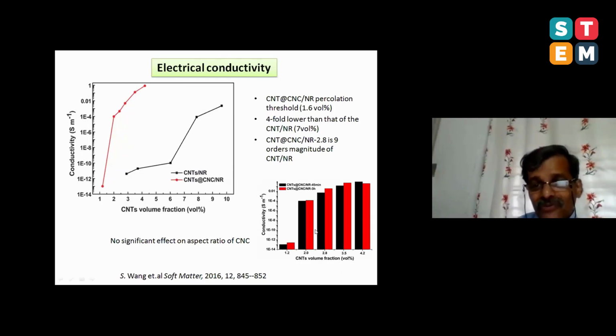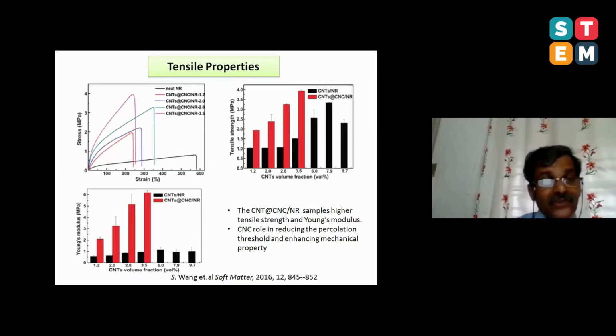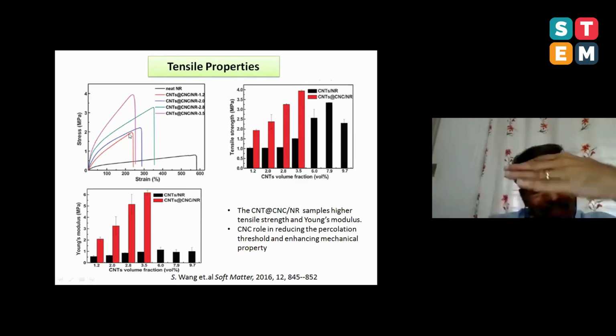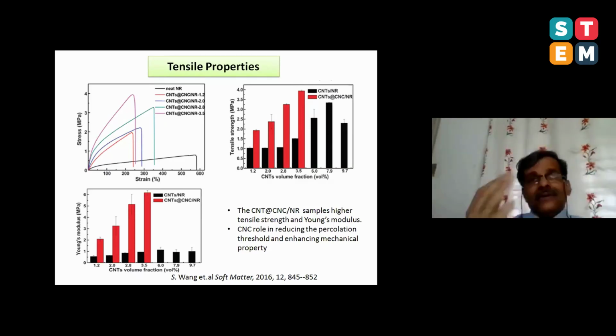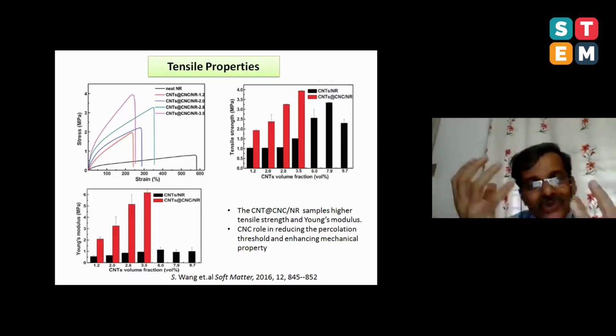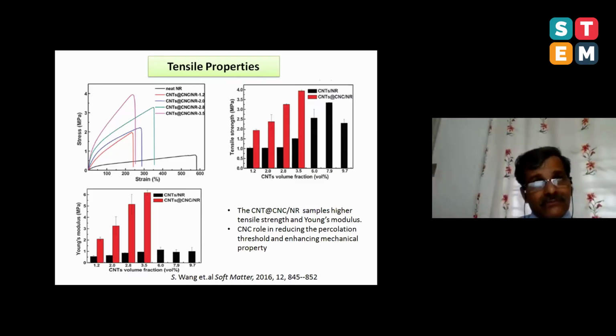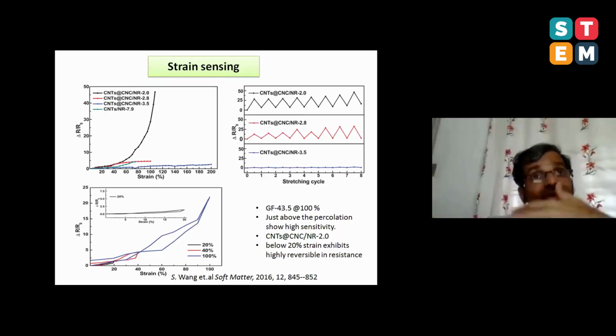Look at the conductivity performance. Conductivity is much better. Look, mechanics is much better. Look at this, this is neat natural rubber. This is a combination of CNT and nanocellulose together. If you use CNT alone, you are somewhere over here. Look at the red. So you get lots of synergistic effect when you combine nanocellulose and CNT together. This is something very interesting. You get enhanced percolation process. You get very good mechanics. Similarly, you can also use it for strain sensing.